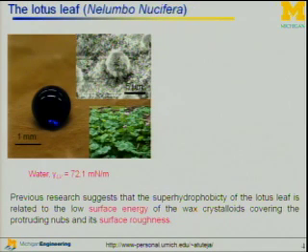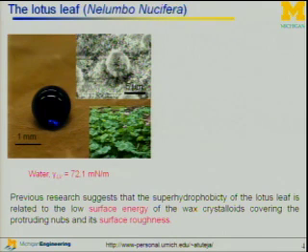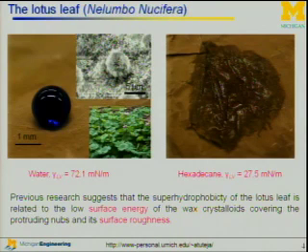Not only can we make these surfaces, but they can be found in nature too. An example is the lotus leaf. Previous research suggests that superhydrophobicity of the lotus leaf is related to the low surface energy of the wax crystalloids covering the protruding nubs and its surface roughness. As you can see, water with a surface tension of 72.1 yields an extremely high contact angle on the surface. However, if you have a lower surface tension liquid, such as hexadecane with 27.5, it will wet the surface.